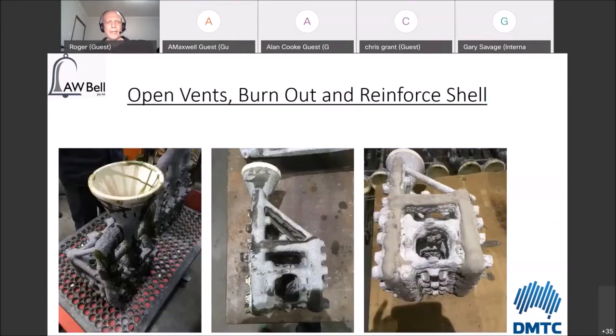So here, the next thing, you open up the vents. On the left-hand side, open up the vents, remove as much of the wax as you can with a hot air gun, burn it out, and you can see the middle one is the burnt out part, where all the vents have been broken, the ceramic's been broken off to open the vents. And then on the right-hand side, the shell's being reinforced.